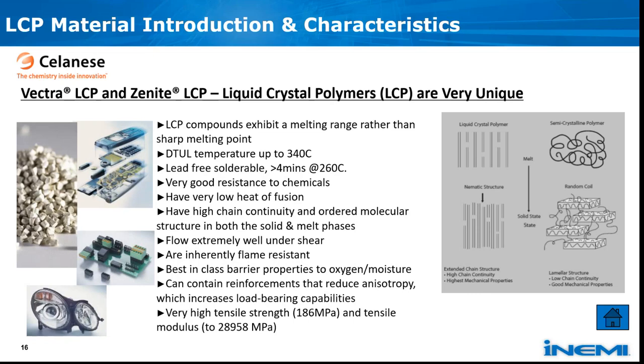LCP has a very good thermal resistance, and its DTUL temperature can go up to 340 degrees C. Based on that, it can work for the lead-free solderable process. Regarding the molding ability, it has super good flowability on the proper shear and still without flash issues because it's with the low heat of fusion. It's really a very good material candidate for those thin wall with complex geometry like the high density CPU socket.